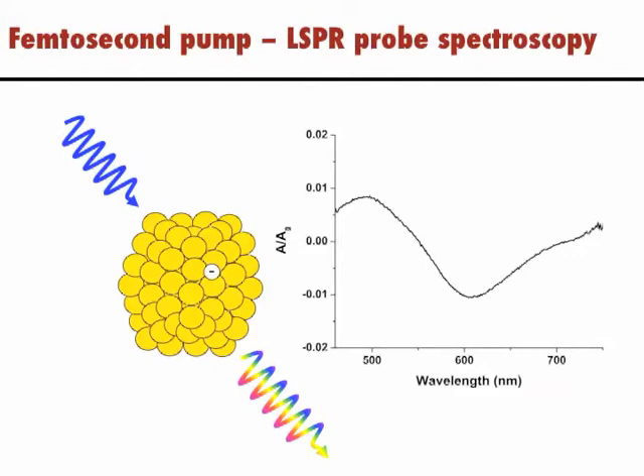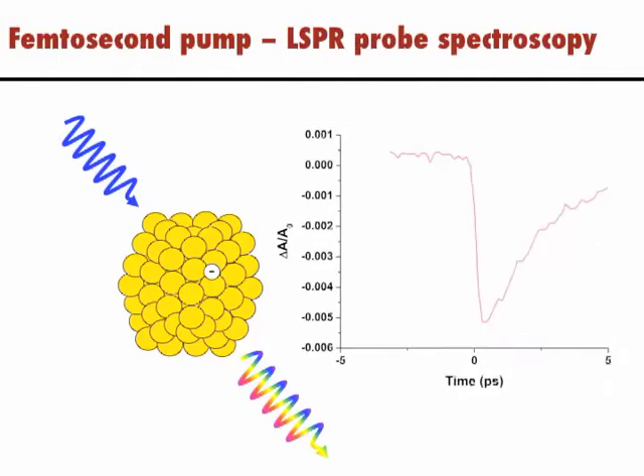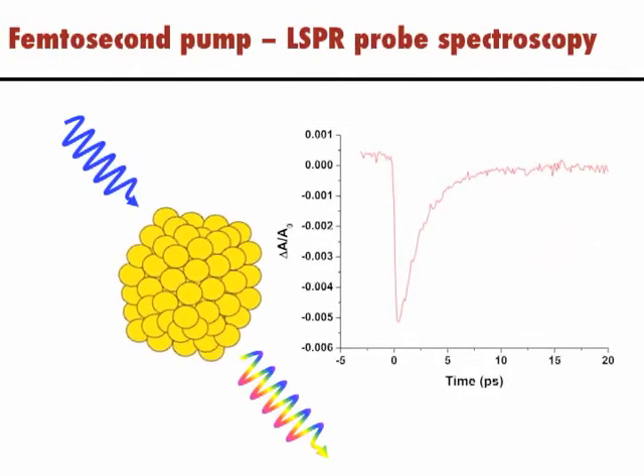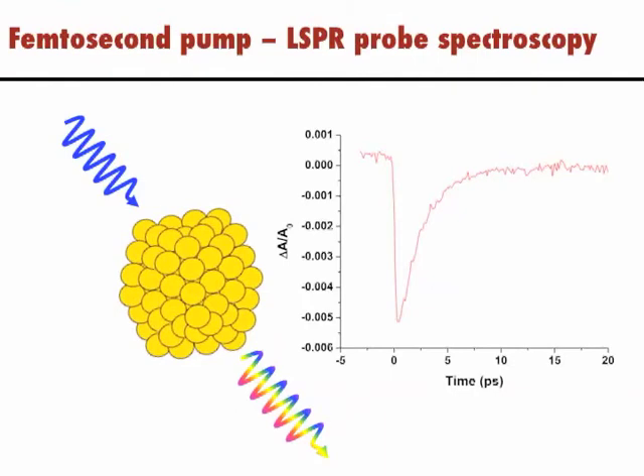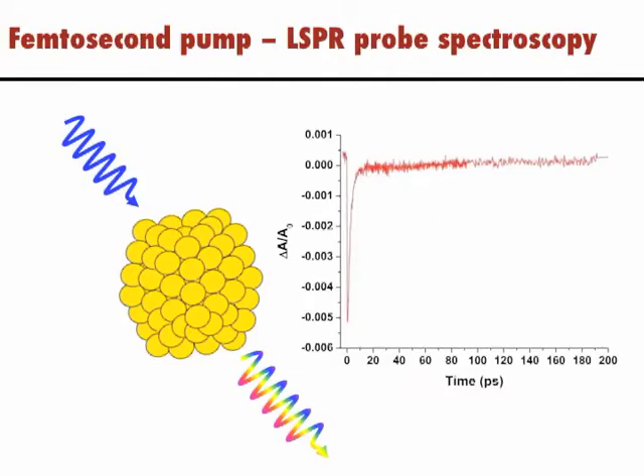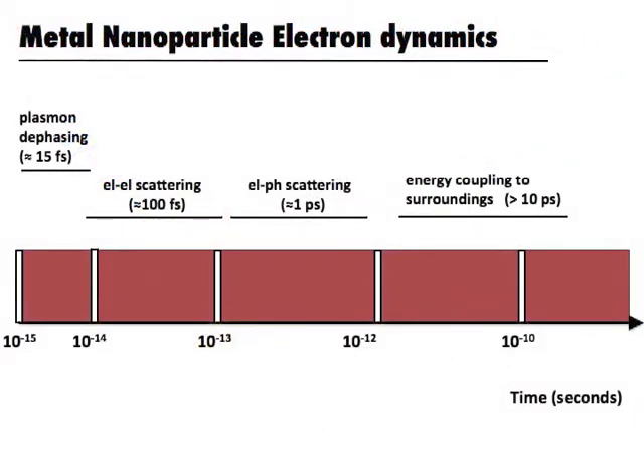These hot electrons cool through a three-step process that involves ultra-fast electron-electron scattering, picosecond electron-phonon coupling, and energy coupling to the surroundings over timescales ranging from tens to hundreds of picoseconds. The latter process heats the surroundings and changes the interfacial dielectric properties. The large difference in timescales for plasmon dephasing and interfacial heating are key to these studies.